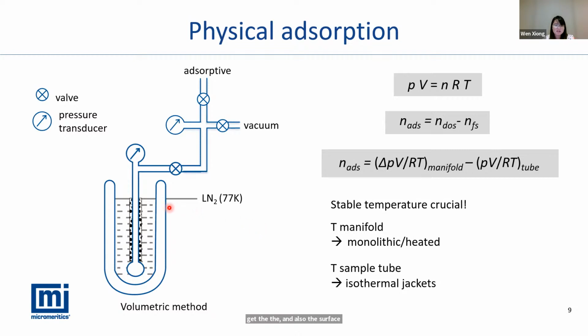The left figure shows a schematic of the volumetric adsorption setup, which is a very easy setup. Normally it consists of three different valves: one to the adsorptive, one to the vacuum, and the third one to the sample tube. Depending on the instrument model, we have different ranges of pressure transducer to measure different adsorption limits. With the pressure transducer, we are able to measure the pressure change during the adsorption. That is the core of all the testing.